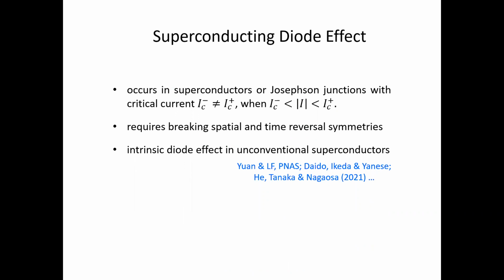Since then, there have been many, many theoretical and experimental papers on this subject. This field is expanding quickly. Basically, the superconducting diode effect occurs in superconductors or superconducting Josephson junctions in which the critical currents in the forward and backward directions are different. In this case, when the applied current is in the intermediate range, we will get 100% diode effect, okay? And this obviously requires breaking the symmetries, the spatial inversion, and most likely time reversal symmetry as well. The experiment I just showed you involves an artificial superlattice. So there's now a lot of interest in finding unconventional superconductors, which by themselves break the symmetry and should lead to an intrinsic diode effect.